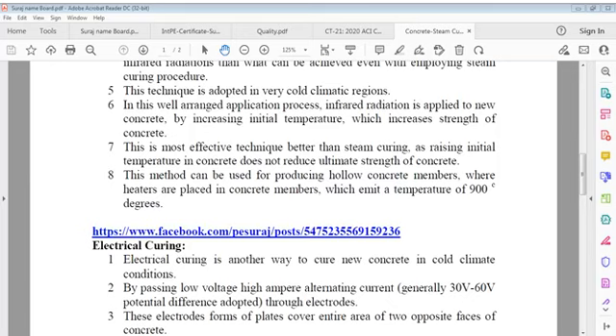This is the most effective technique, better than steam curing, as raising initial temperature in concrete does not reduce ultimate strength of concrete. This method can be used for producing hollow concrete members, where heaters are placed in concrete members which emit a temperature of 900 degrees Celsius.